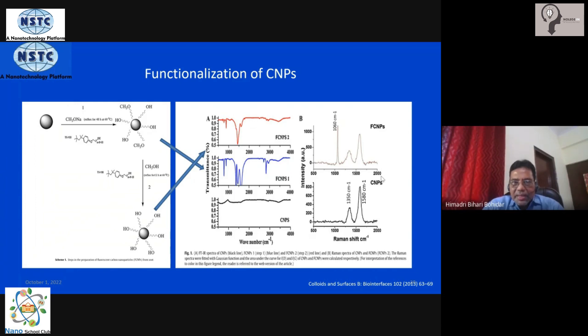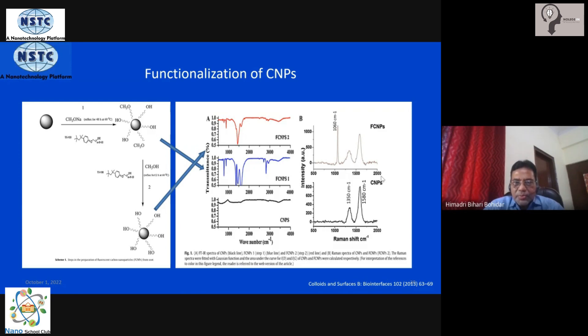That is the first level conversion. In the second step, we reflux it with methyl alcohol — methanol — for about 12 hours, again at the same temperature. All the CH3O groups disappear, and the surface gets fully functionalized with hydroxyl groups. If you have hydroxyl groups on the surface of a particle, it can be bound to various different kinds of molecules — they are very friendly.